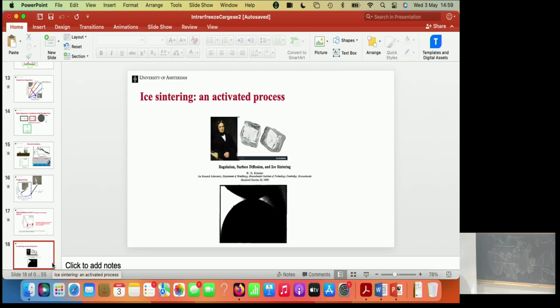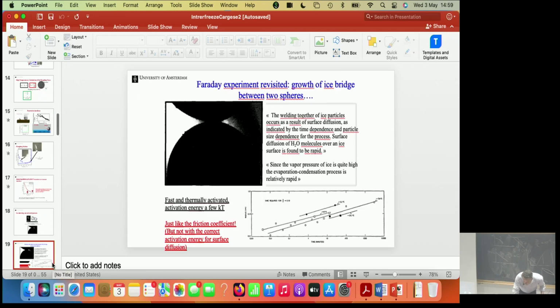He redid that in a controlled way. He had two ice spheres in a freezer. He brought them into contact, and then magically the neck between the two spheres began to grow. And that allows you to quantify the qualitative remarks of Faraday. And so the result is very interesting, because he also says that there need not be any liquid. He says the welding together of ice particles is a result of surface diffusion. So things can diffuse simply from the boundary towards the neck. And so he has some data, not a lot of data, that actually substantiates that mechanism.